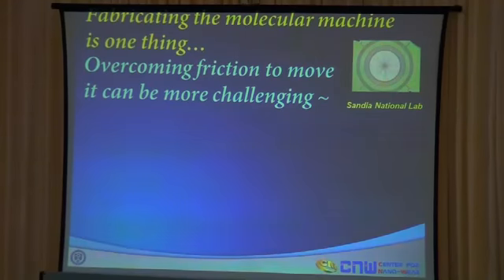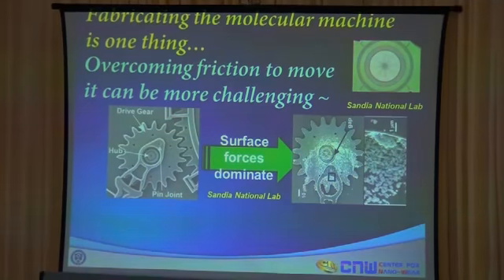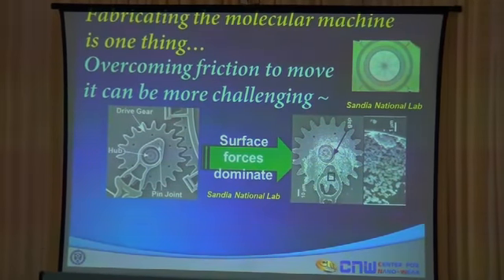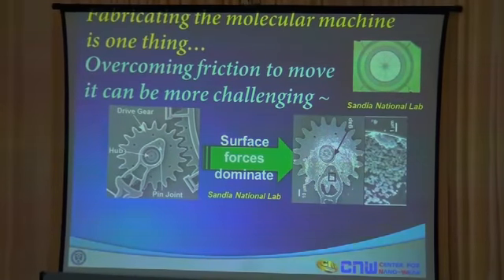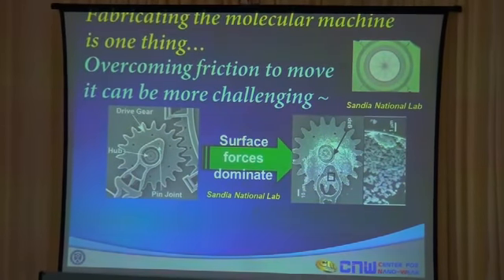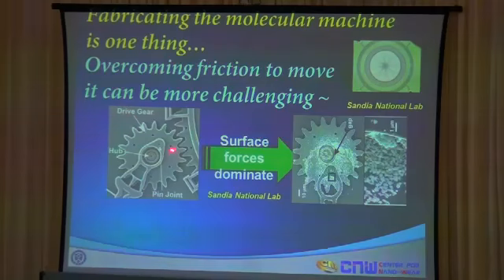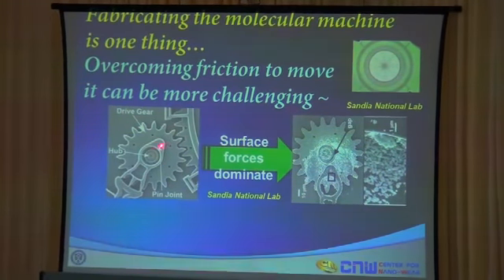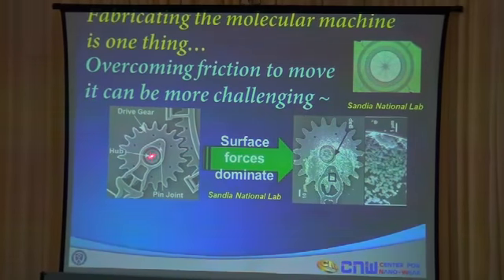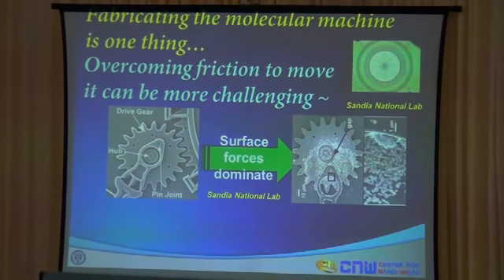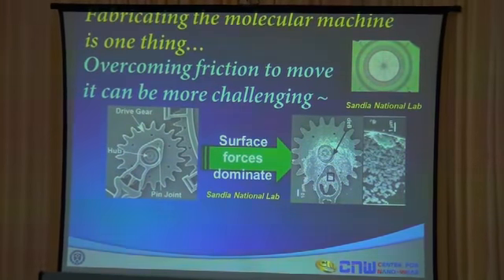Now what is the reason why, despite the fact that this kind of very fancy MEMS component was developed many, many years ago, we do not have a commercial product? The reason is because we cannot overcome the surface forces, which become so dominating, especially at micro scales. So this is an example of a micro gear composed of many mechanical elements at micro scale. We start running this component, and because of surface forces, it fails and it's not reliable.